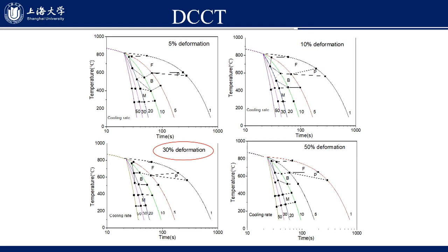It is clear that deformation greatly increases the start temperature of ferrite transformation and causes the ferrite phase range and bainite phase range to move significantly to the upper left side, and enlarges the ferrite phase range of the steel. The martensite start transformation temperature increases from 360 degrees C to 400 degrees C. The critical cooling rate increases with the deformation increasing, to 20 degrees C per second for 5% and 10% deformation conditions, to 30 degrees C per second for 30% deformation, and to 50 degrees C per second for 50% deformation condition, respectively.